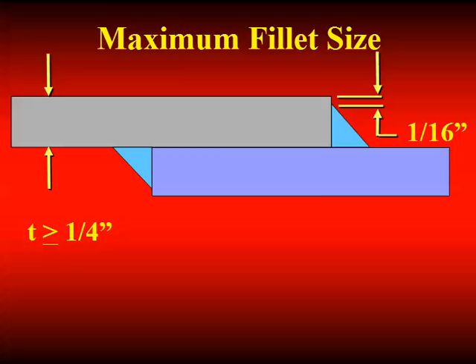And then you stop and think and say, well, it complies then. Yeah, it complies, but that's kind of a stupid corrective action. He said, well, I want to teach the welder a lesson. Well, there's probably other ways to do that, too. In any event, if we know the edge is there for the rest of the weld and only a portion is melted away, we're not concerned about that. So it's good to understand the background behind that. Now, why does this only apply for thicker material? Because for thinner material, the problem is melting through the whole thing. You can't just melt away the top edge and not melt through the whole cross-section. So it's applied to thicker material.